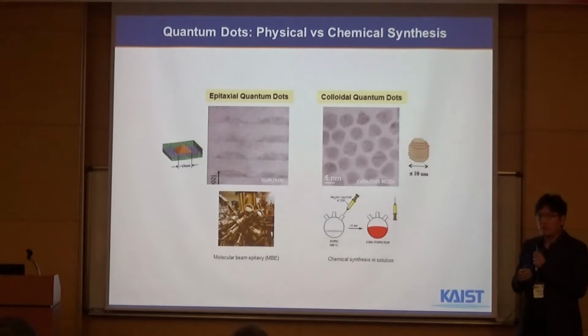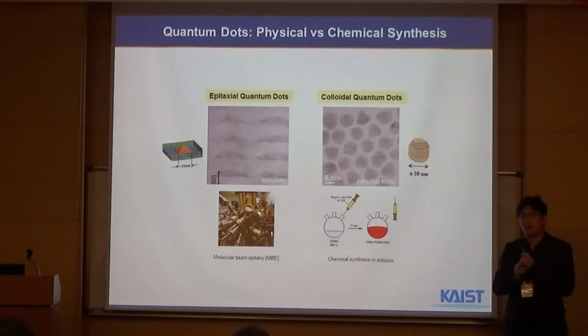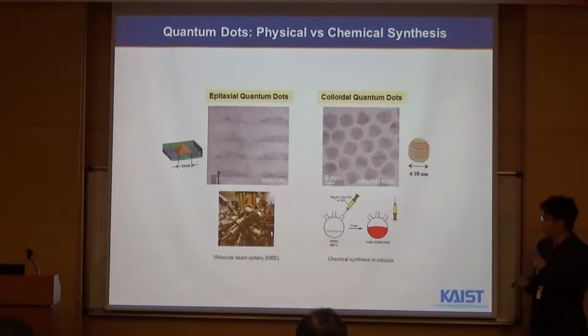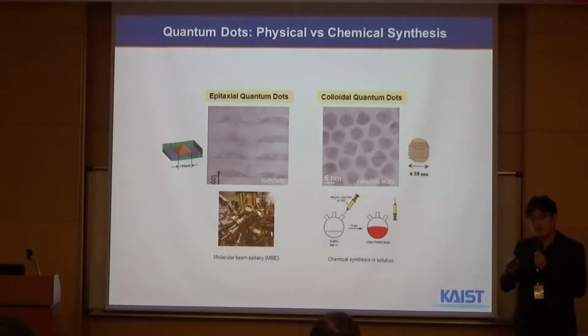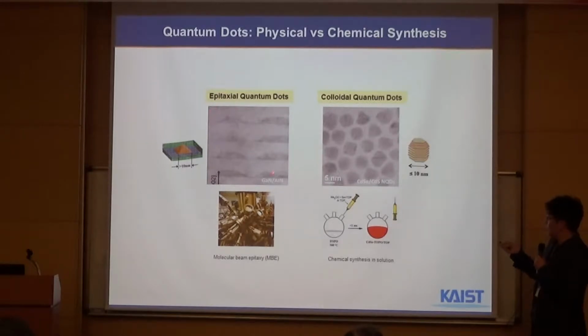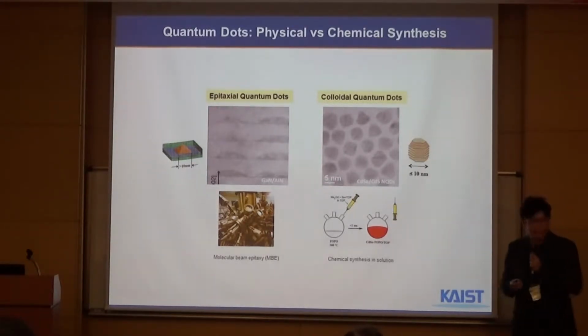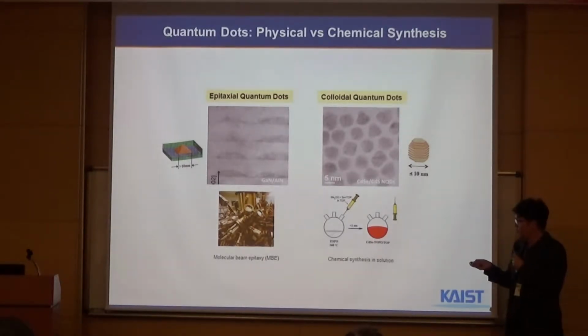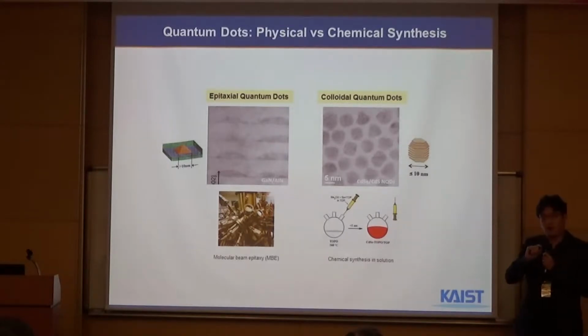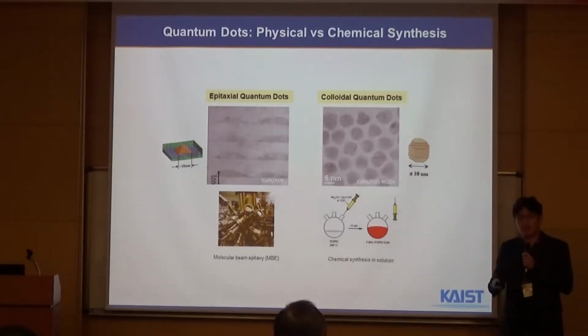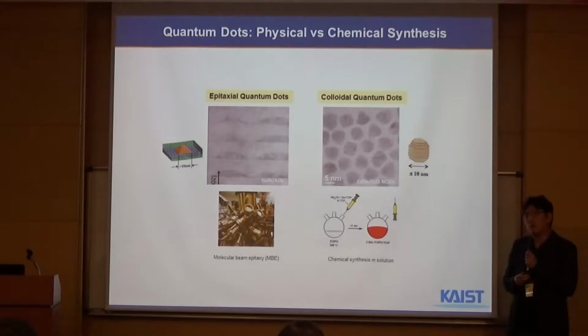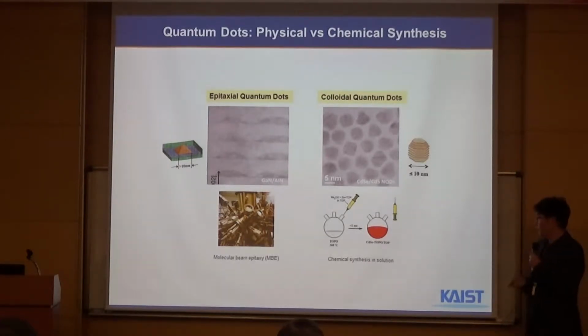So if you think about this, of course, quantum dots can be made in several different ways. You can classify the synthesis into two, one being the physical method. You can bombard your substrate with very high energy and create crystals within a matrix, which people typically call epitaxial quantum dots. Using high vacuum chamber equipment, for example, molecular beam epitaxy creates these finely size-tuned quantum dots within a matrix. Or you can make nanocrystals or these quantum dots in a chemical way. Chemically synthesized quantum dots. Colloidal quantum dots is one very important example.